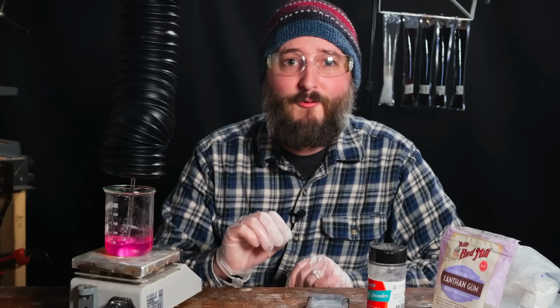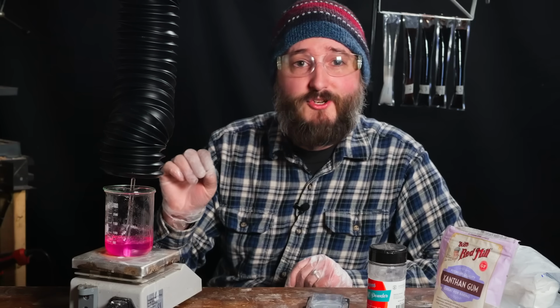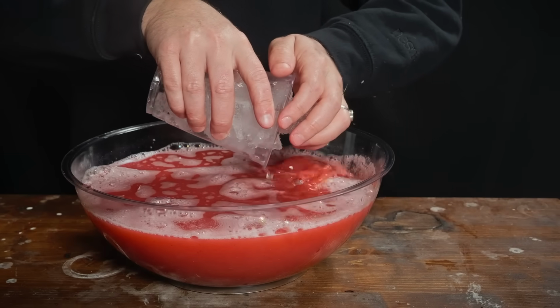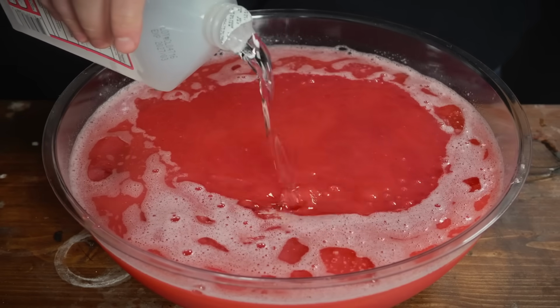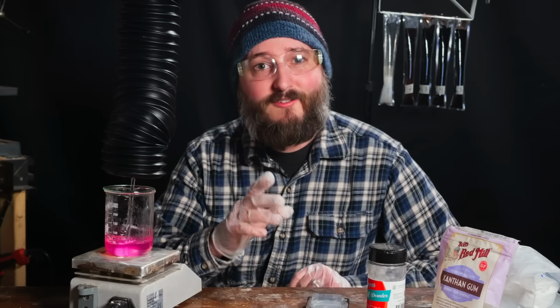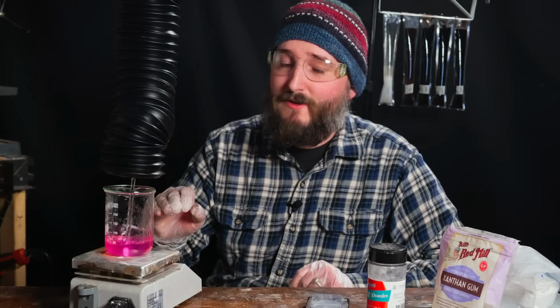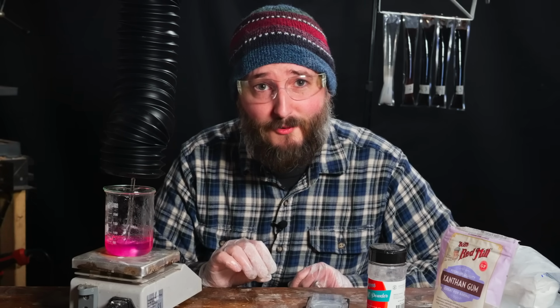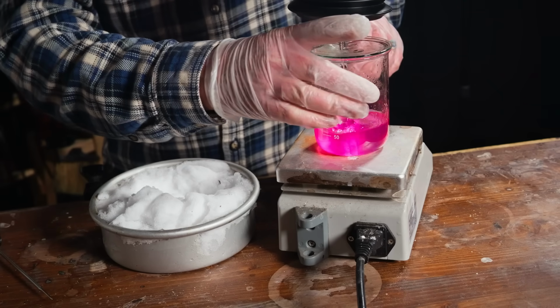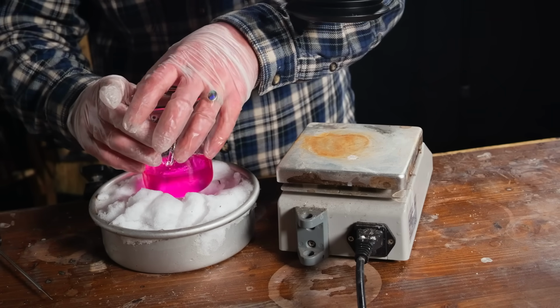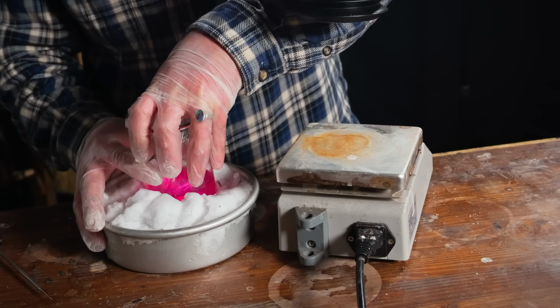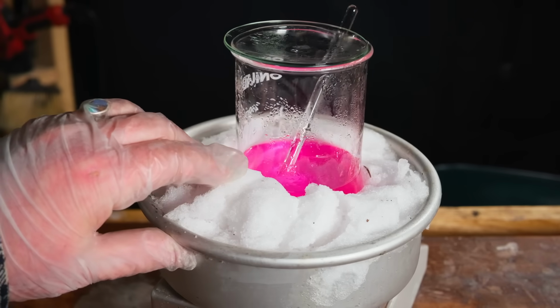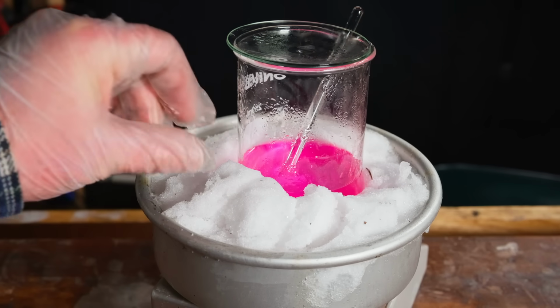First, I'd like to see if we can separate the CMC by a much faster technique, which we used in my previous video to separate DNA from strawberry juice. This involves chilling the polymer solution down to as cold a temperature as possible, and then adding chilled isopropyl alcohol over top. This should form its own separate layer, and hopefully cause the sulfonated CMC to precipitate at the boundary between the water and alcohol.